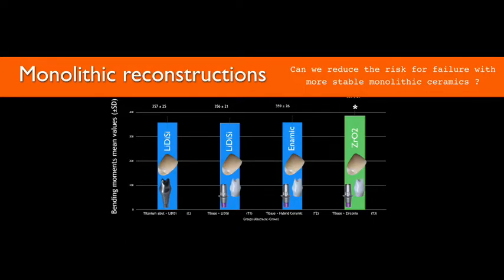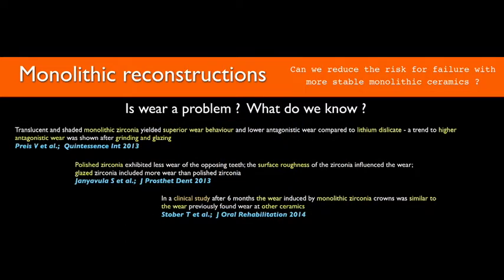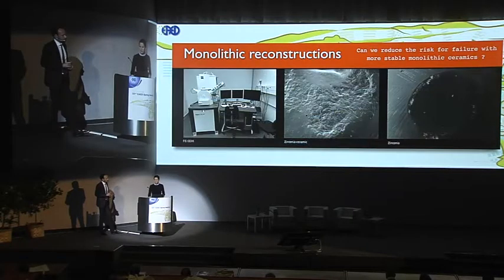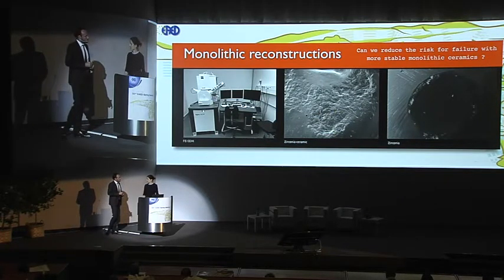But now, introducing these very hard materials, Irena, is that a problem for the oral cavity? Well, it can be a problem if the monolithic materials are not high gloss polished and the surface is rough or maybe has some wear due to occlusal contacts. A number of studies have shown that this induces significant wear of antagonists, being either natural teeth or reconstructive materials. And you can see this also on the samples that we've analyzed.